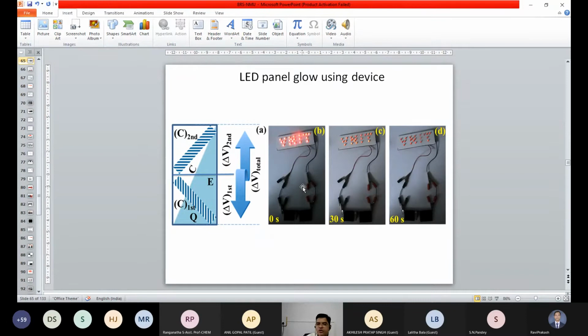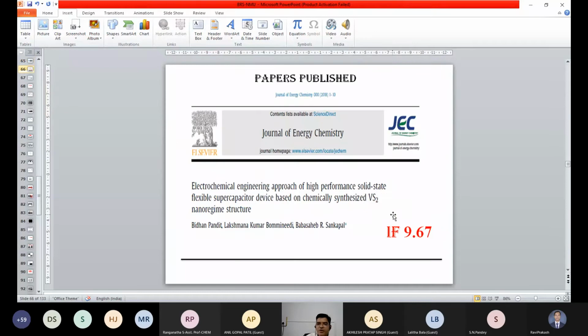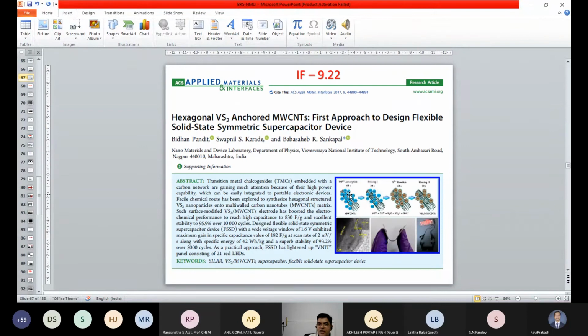We have charged it for a short time, and then it is discharged through this panel, and it runs up to 60 seconds. This result is published, just vanadium sulfide on the stainless steel, that we have published inside the Journal of Energy Chemistry. And when we coated this vanadium sulfide on the carbon nanotube, we have seen it has a hexagonal shape, and this was published inside the ACS Applied Material and Interface Journal. Right, and we have focused on the hexagonal shape of the vanadium sulfide anchored on carbon nanotube.